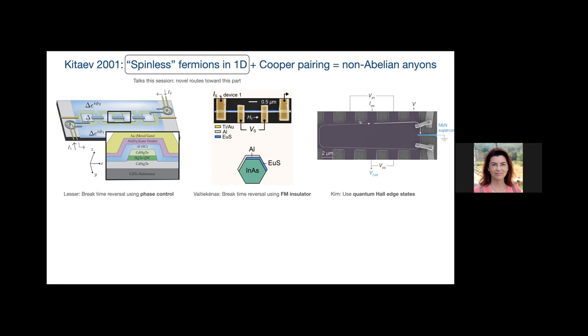Okay, yeah, I think my comment or question was more the way to think more physically about how the state in the nanowire acquires all of the superconducting and magnetic properties. I would say that basically part of the wave function leaks into the europium sulfide and another part into the aluminum, right? Yes, that is what we're doing. That is why we include in the numerical calculations both the aluminum and the europium in the tight binding calculations on the same footing, because you want to have your wave function be able to enter the superconductor and also partly the magnetic insulator. So this is indeed necessary to get these proximity effects. And it happens exactly because it penetrates, yes. Yeah, but I guess my thinking from there is that it's basically not possible to have topological states without the europium also affecting the other one, right?